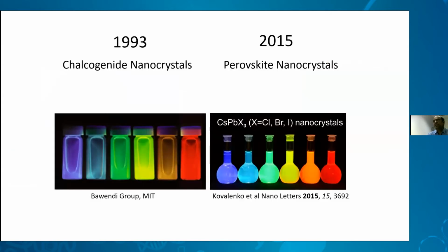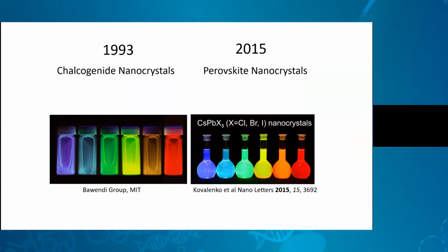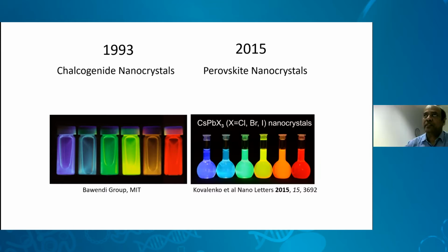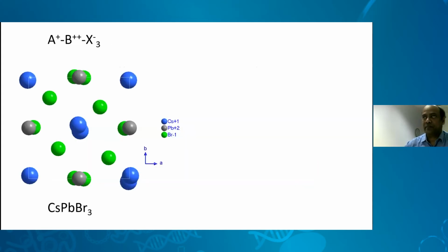And two types of materials are in this category. One is from 1993, three decades have passed, for the cadmium selenide quantum dots, and recently Maxim Kovalenko has been coming out with a new strategy, new materials. This is cesium-lead halide, or so-called perovskite. This has been in the last 5 years. This has now become one of the most in-demand energy materials, both for light emitting and photovoltaics. What is this material? An ABX3 type of material. A cesium-lead bromide, it is a stable one and green emitting, and one of the demanding materials.